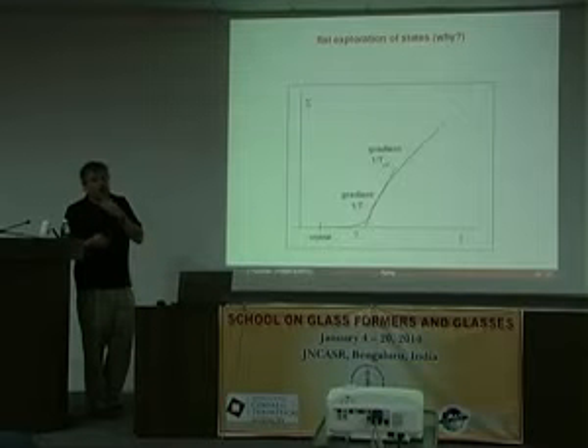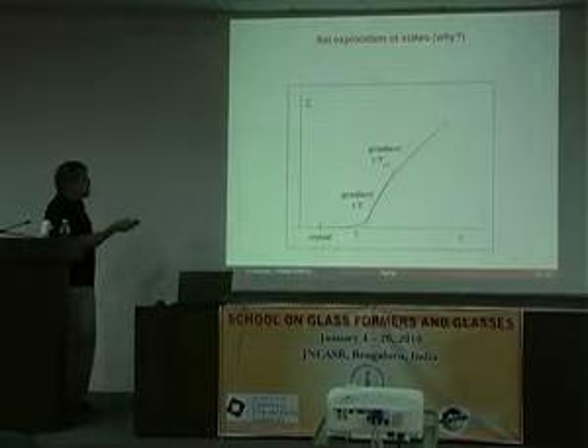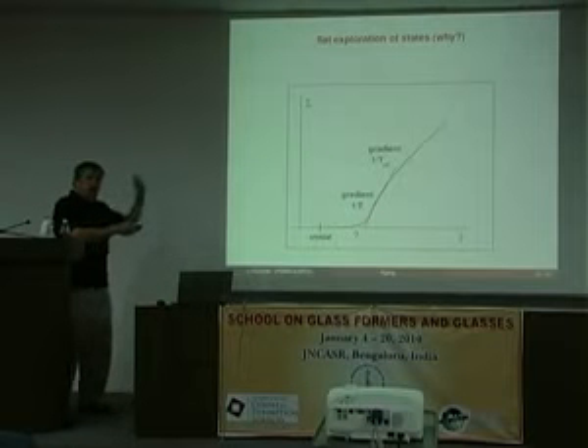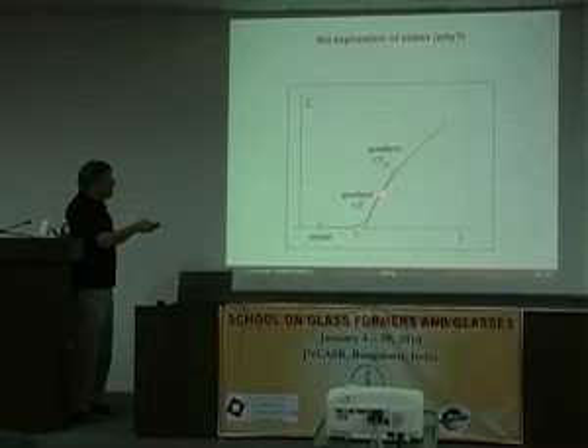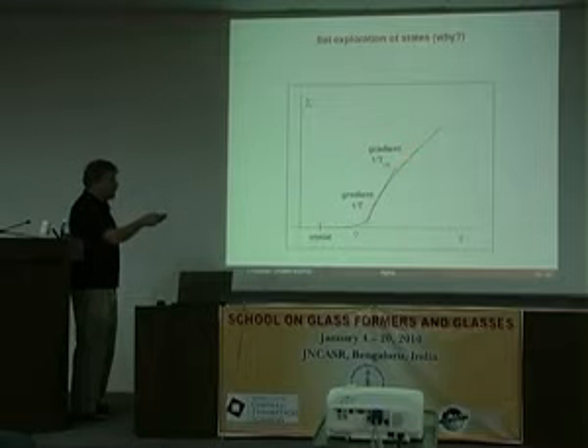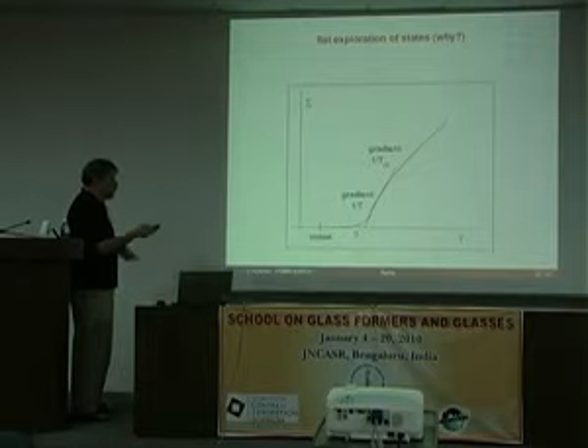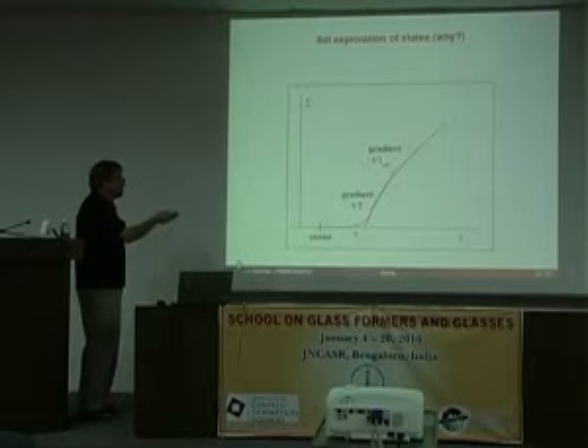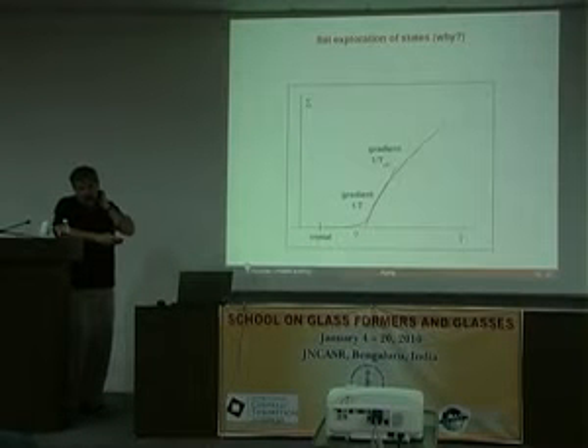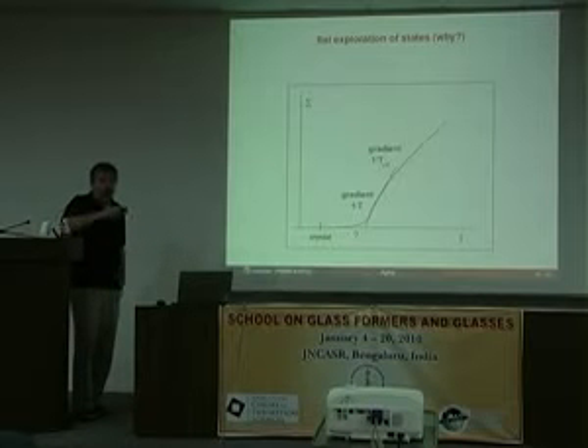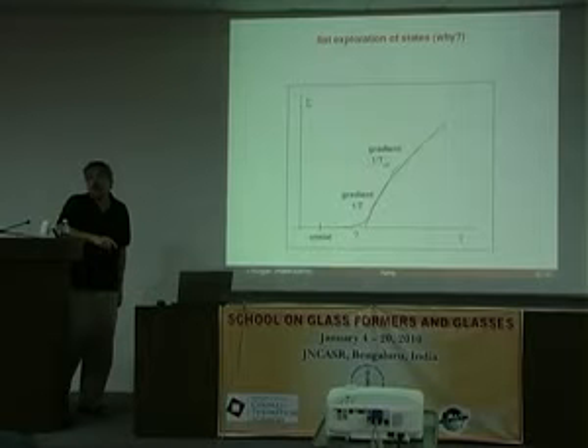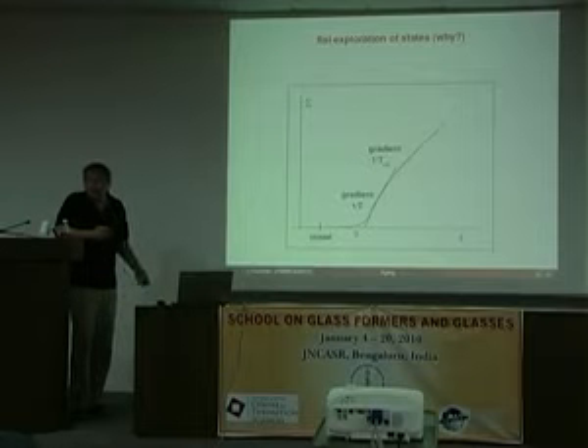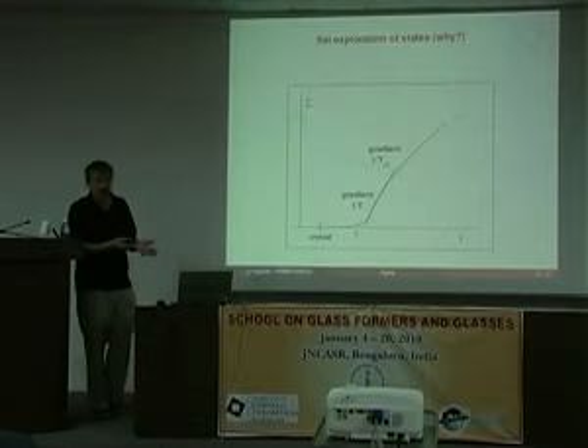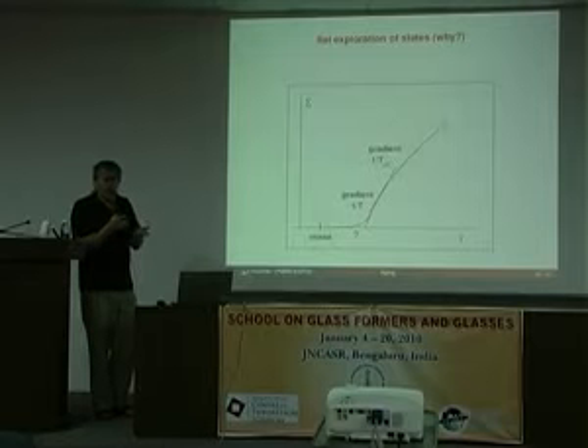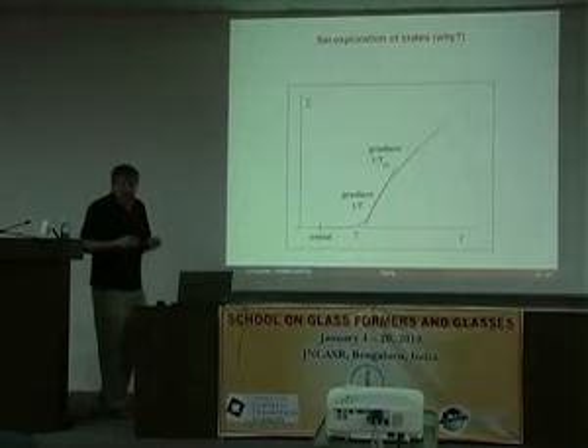But we already had some in the context of Edwards with Bulbul, is to think that these are all the states in the plot I did previously. If, because of aging or because of stirring, instead of being at this point where in equilibrium you would have 1 over T, you are visiting the states of this height, then if you assume that these states are populated homogeneously, you would get that the effective temperature would be related to this landscape. This is closely analogous to supposing that you're hopping between excited states and visiting them flatly. But then again, if this is the case, we have no idea why this would happen flatly. It is a fact that when you solve the equations, you see the effective temperatures, and it is also a fact that when you look at the expectation values, they correspond to what you have here. But why this should happen, we don't really know.